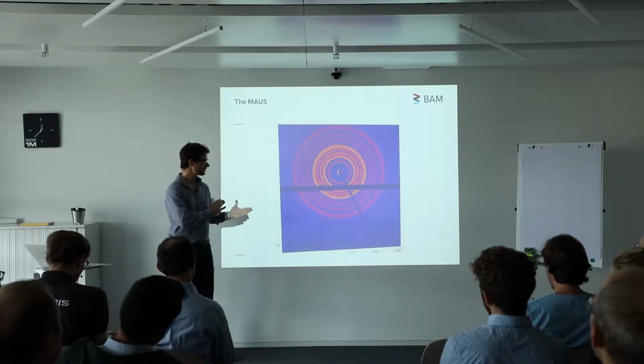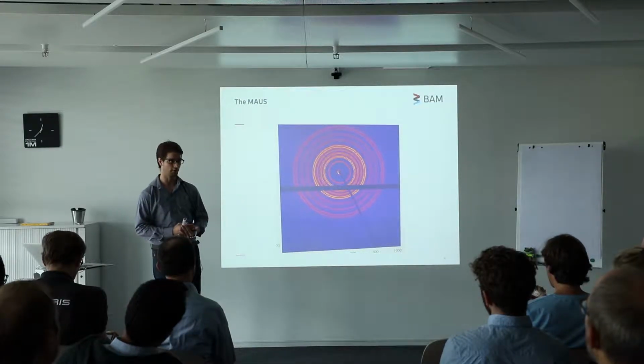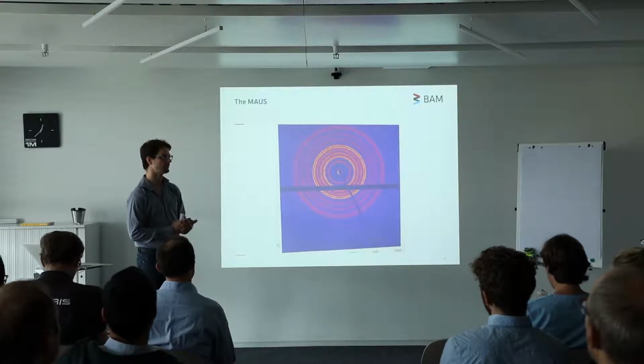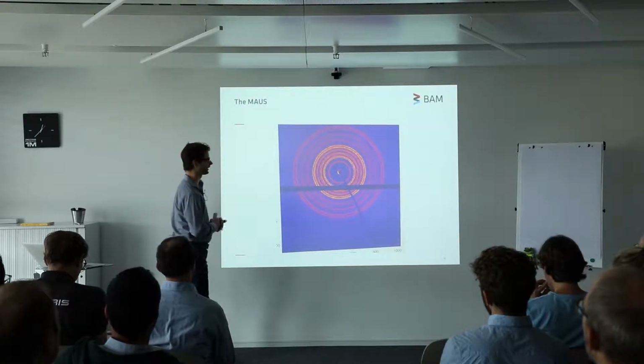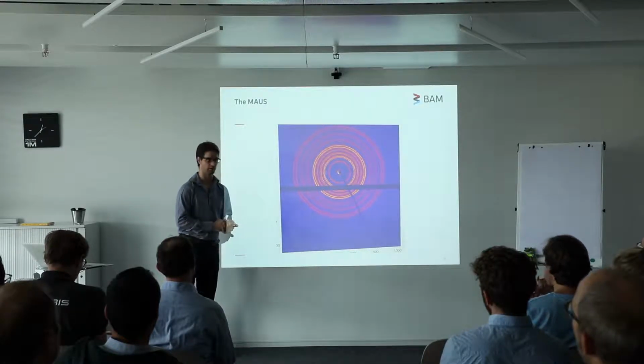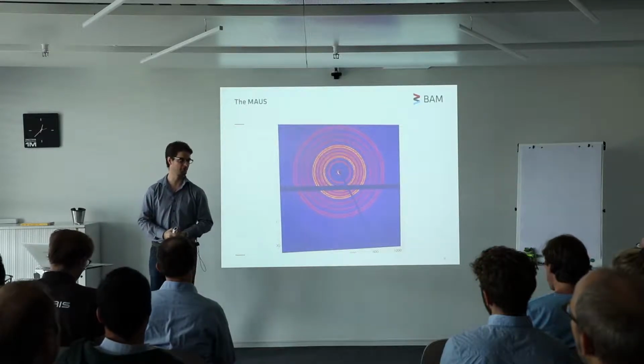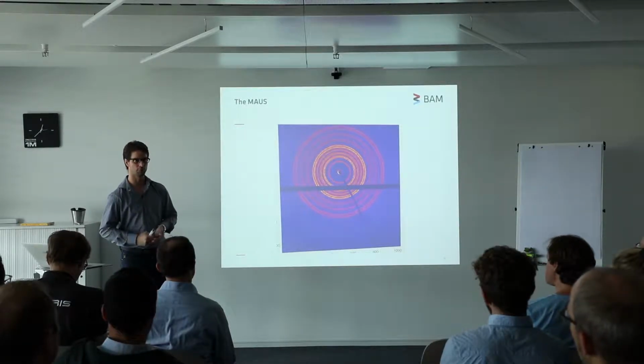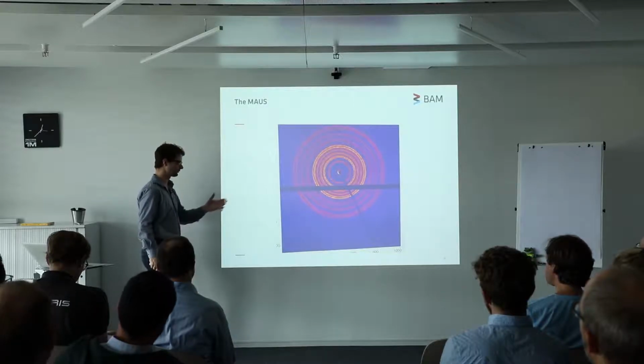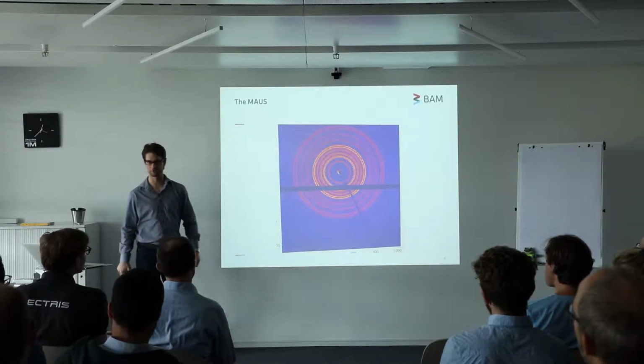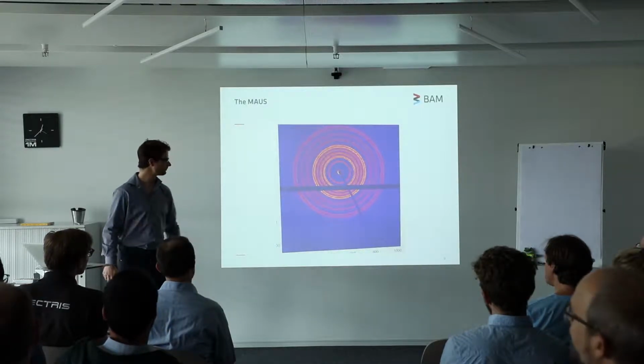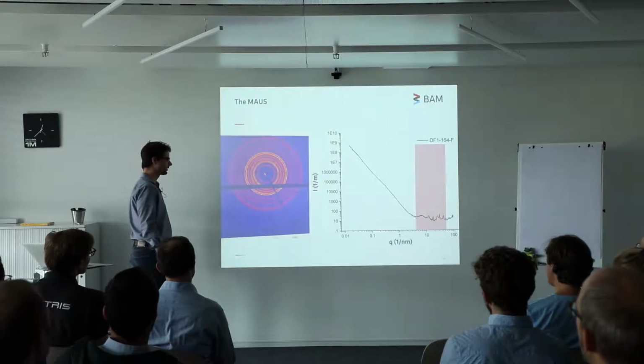So the data collection is in 2D. The data corrections are also all done in 2D. So if you have texture or orientation in your sample, then you can get a nice corrected scattering pattern in the small and the wide angle regime in 2D, and then you can let your two-dimensional fitting algorithms loose on this. Anyway, so we have a moving detector.